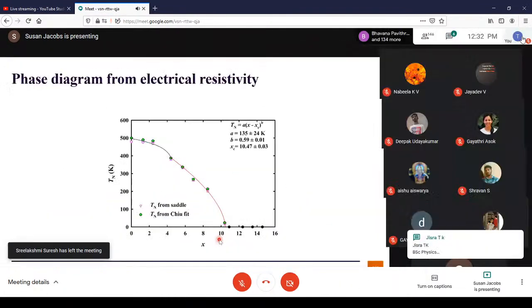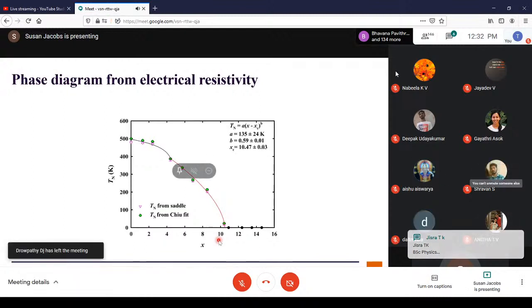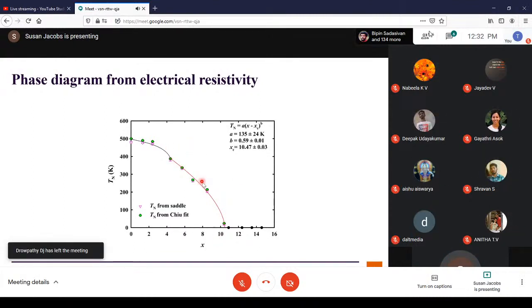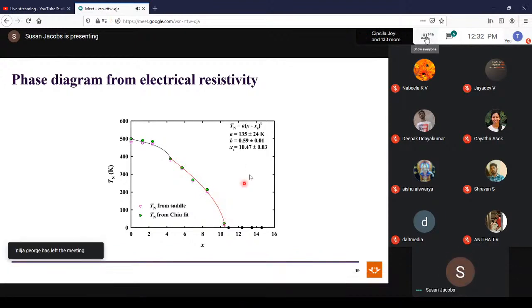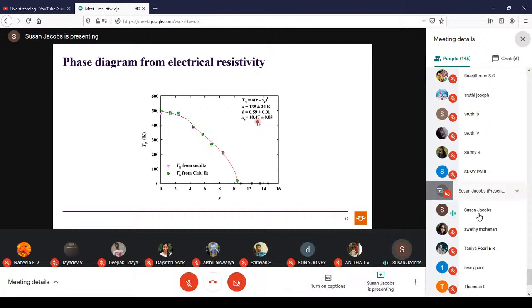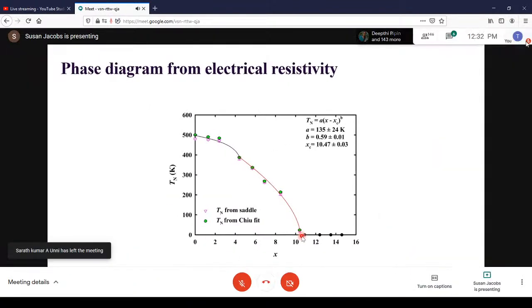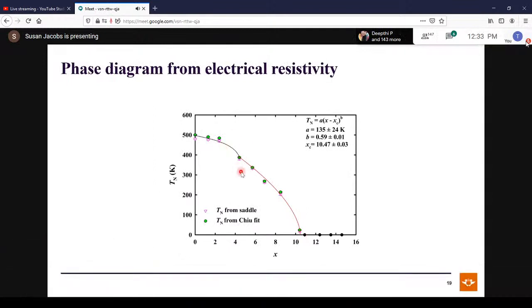Okay, so we constructed a phase diagram from our electrical resistivity measurements. This red curve over here is a power law fit of the form given there, and we saw the critical concentration was 10.47, very close to 10.5. So antiferromagnetism is suppressed, and the transition is suppressed to 0 Kelvin at about 10.5 atomic percent vanadium. The pink triangles are Tn from the minimum point in the resistivity curve, and the green circles are from the fit. We can see there's very good agreement between the two values.